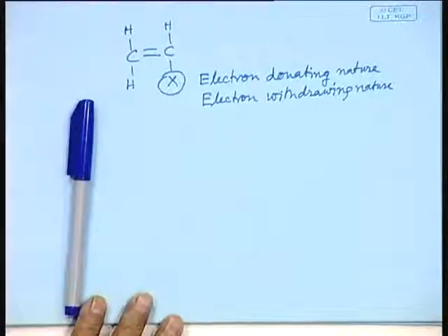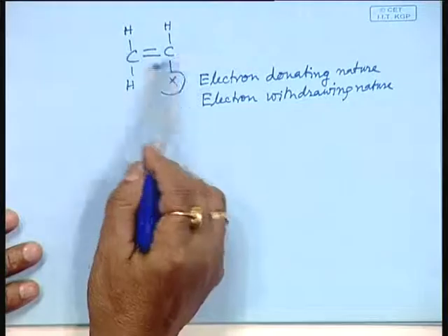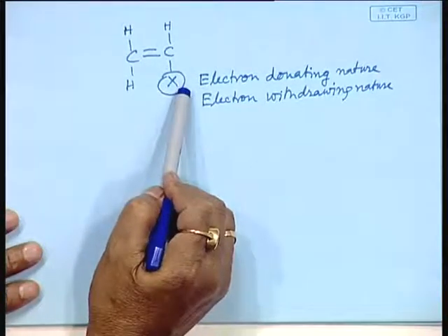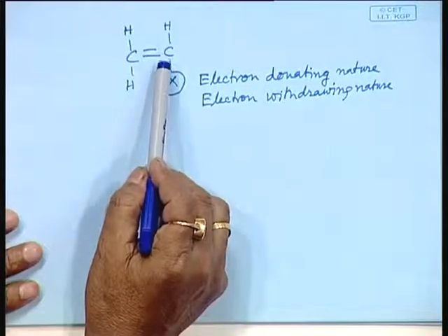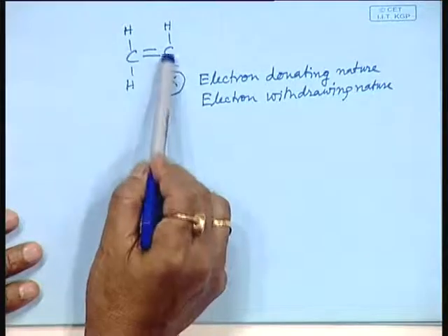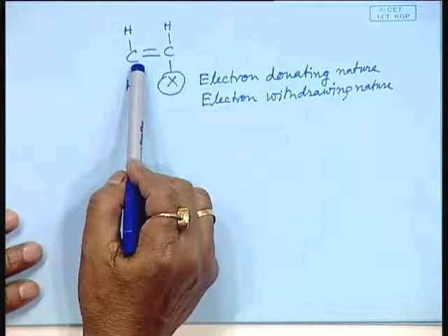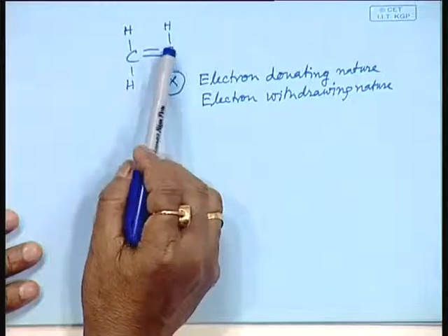So, you can ask, sir, what is the necessity of taking this concept into account? Yes, there is a necessity. If you want to design a new polymer, to synthesize a novel polymer which is non-existing today, then you have to start with a monomer. What kind of monomer should you take? If it is an addition chain polymer, you think of a substituent which is electron rich, which can donate electron to this system. If it donates electron to this region, this pi electron cloud will be polarized.